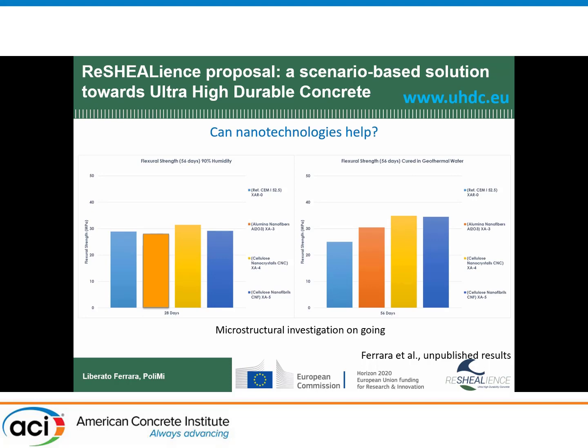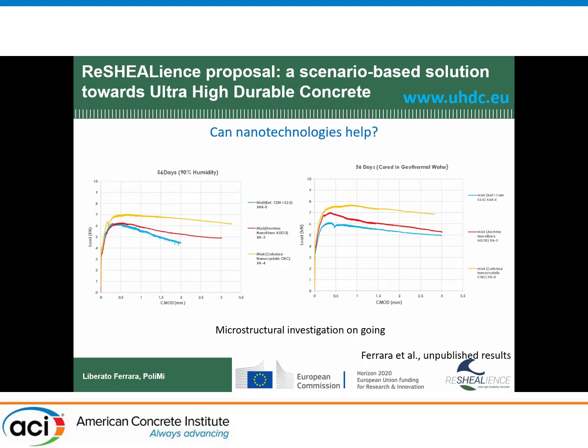So we are going to perform the microstructure investigation. It's probably that these nanofibers do not only close the macro defects and interact with the nano defects, but probably they also leave less space to, for example, the expansive degradation products to grow. And in this sense, we get an improvement of the performance. And this is something, for example, cured in the geothermal water.